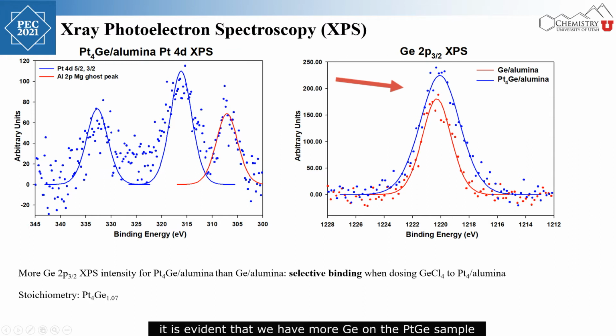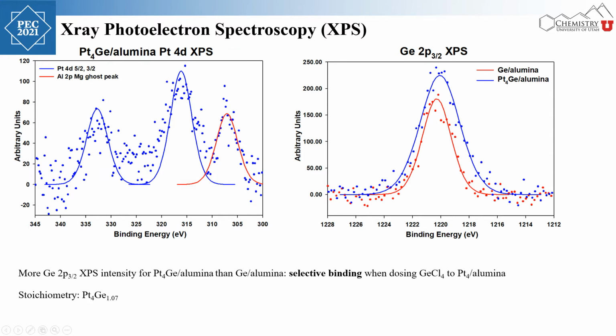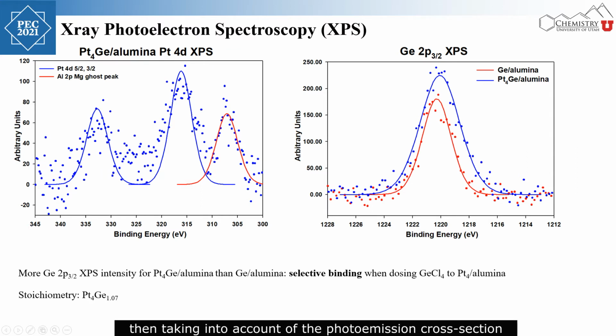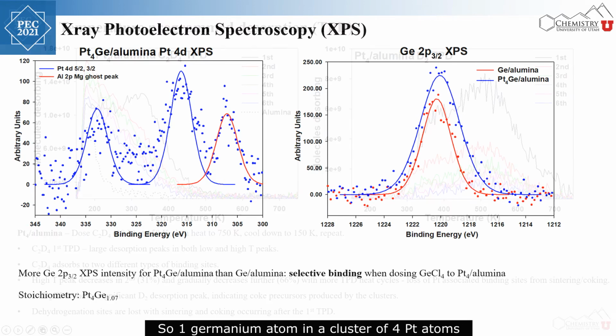It is evident that we have more germanium on the platinum-germanium sample than on the germanium-covered sample. This indicates that the germanium selectively binds to the platinum, thus successfully creating platinum-4 germanium clusters. We can then record the platinum XPS intensities and the difference of the germanium XPS intensities, then taking into account the photoemission cross-section, we can calculate the stoichiometry of the platinum-germanium clusters, which happens to be around platinum-4 germanium-1. So 1 germanium atom in a cluster of 4 platinum atoms.